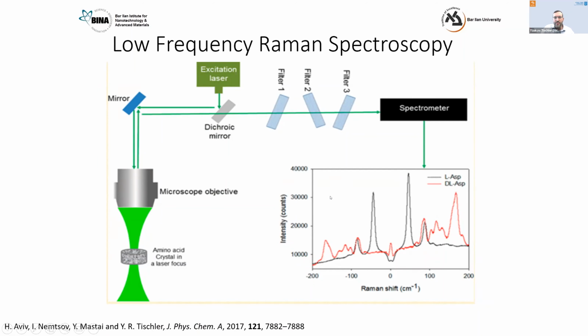Well, I really like this spectrum. This is one of the first studies we did, led by Chagit Aviv in my lab, in conjunction with Irina Nemstev and Professor Mastai's lab, where we looked at the low frequency Raman of a chiral crystal, nanocrystallite film of aspartic acid that was all in the L form, as well as a racemic mixture that was both D and L equally mixed. And what was very surprising is that even though the regular Raman of both L and DL crystals have basically the same spectrum, because they have the same chemical bonds and the same chemical fingerprint spectrum, when we looked in the low frequency Raman, we saw very, very big differences.